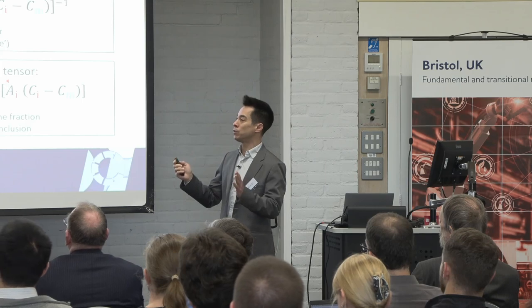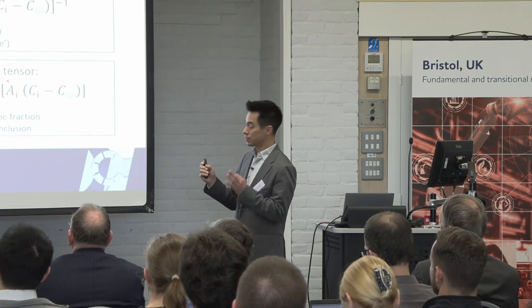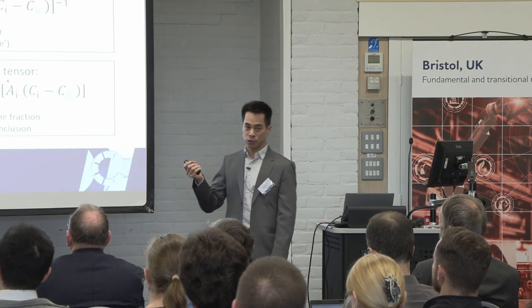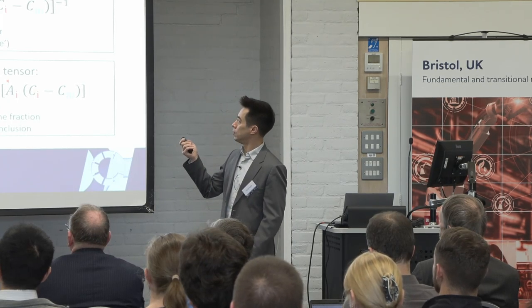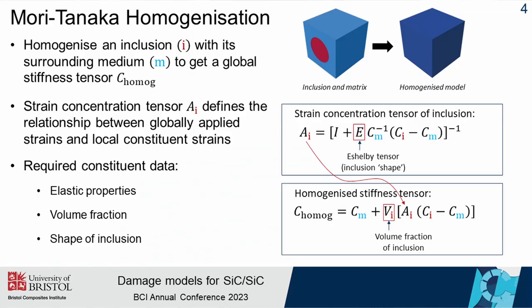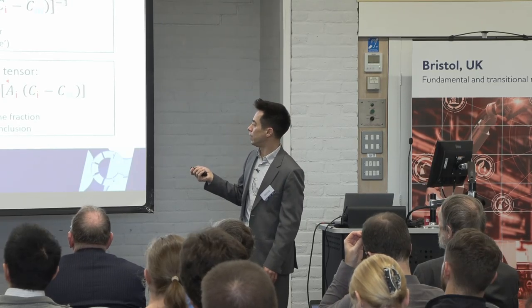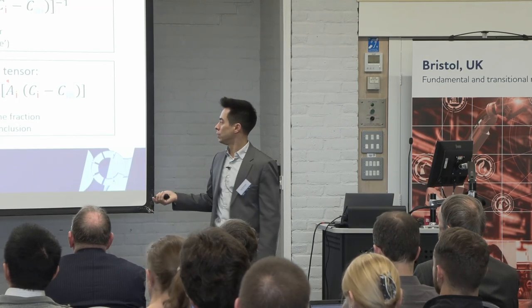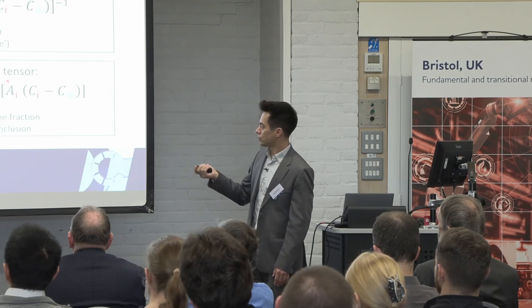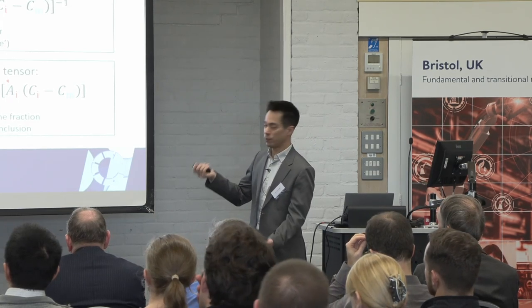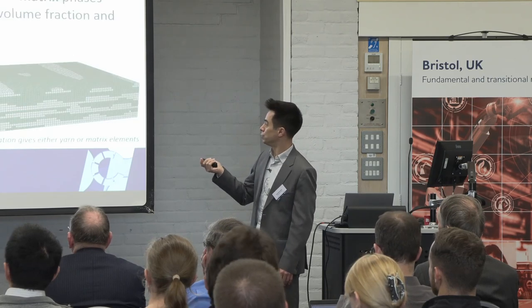Right, so the material models, at least the elasticity part of the material modeling, is based on a Mori-Tanaka homogenization, where, if we have, for example, a single inclusion in a matrix, you need to first compute or define the strain concentration tensor that connects the far field strains to the strain experienced by that inclusion. And then, in possession of that, which depends on the shape of that inclusion, we can derive a homogenized material stiffness tensor for the composite as a whole. So we need elastic properties, volume fractions of the constituents, and the shape of the inclusions.